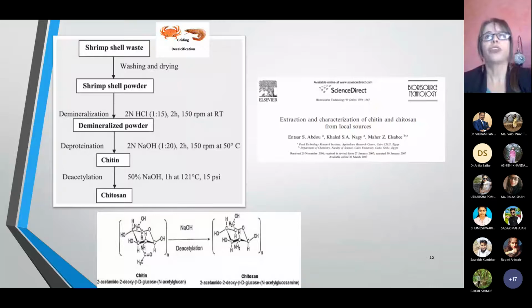In order to obtain another biopolymer, which is chitosan, we have to do the last step, which is the deacetylation, using, of course, sodium hydroxide. Here, for example, as you can see, we have this group. After deacetylation using sodium hydroxide, we can remove this group in order to obtain chitosan.